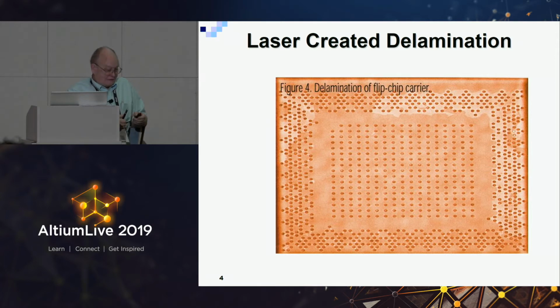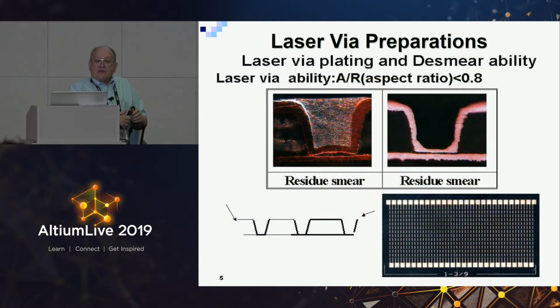And so one of the things is, okay, now we got the hole. Well, unfortunately, we may have resin smear and residue smear in the hole, which you can't discover. These things are 5 microns across, or 50 microns across. You can't cross-section this stuff easily. So what I always demand is that you have a coupon as part of the panel, off to the border, that has a daisy chain.